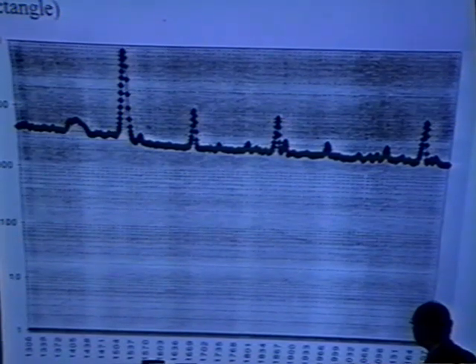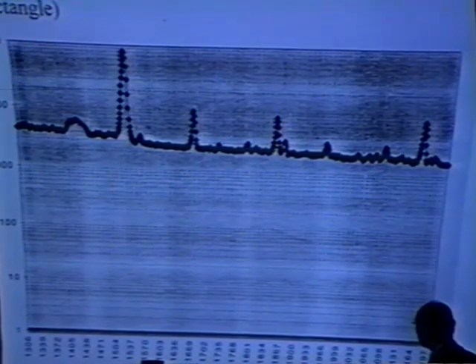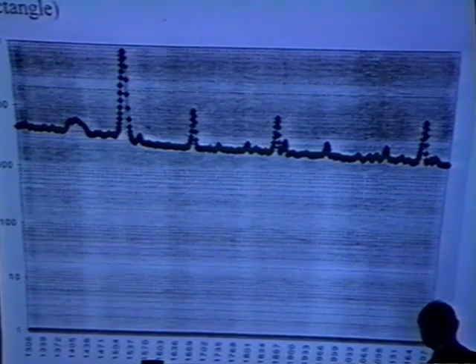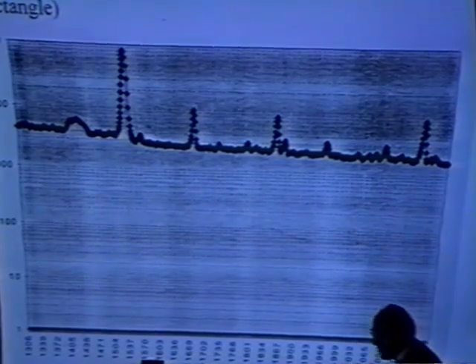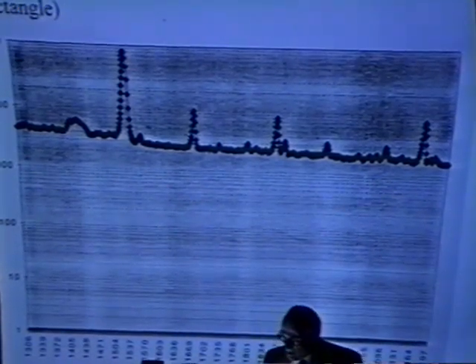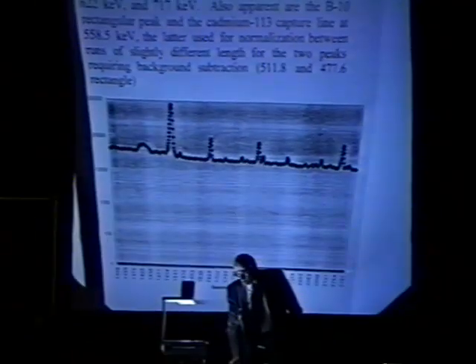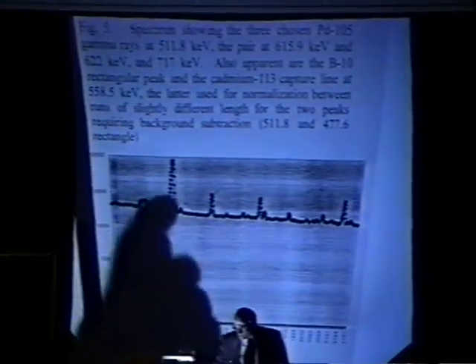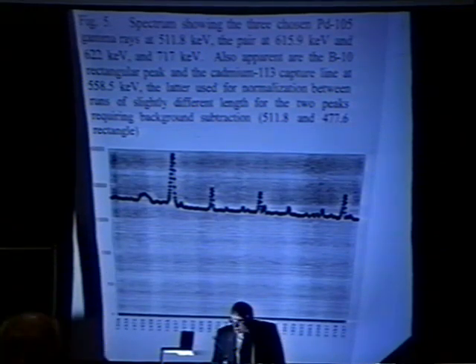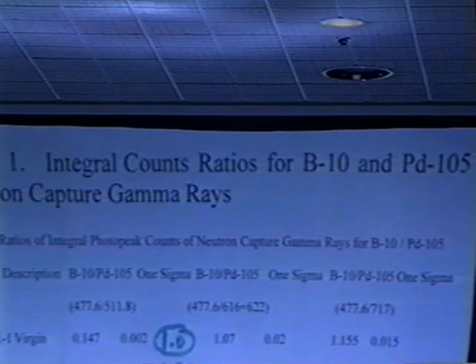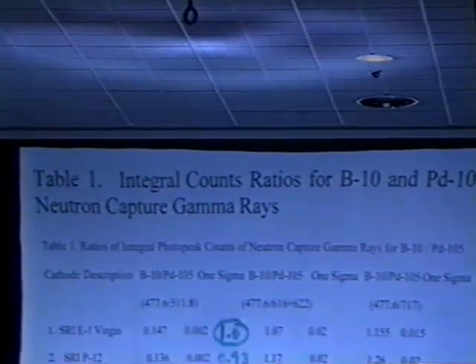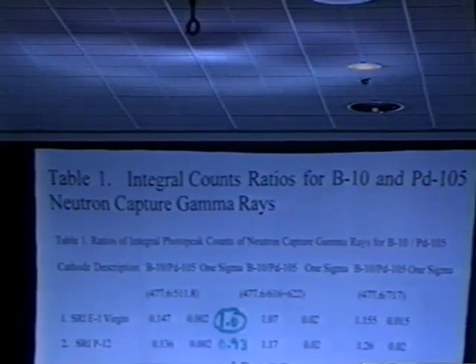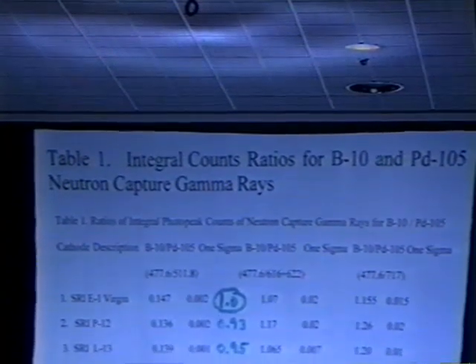And then here's the 616, 622 pair, also from palladium-105. Here's a 717 kilovolt gamma, also from palladium-105. So I have 3 or 4 ways, many others perhaps, to make this relative measurement of the area under these peaks relative to each other for the various cathodes. Now, here's some results, and I expect that you won't be able to do this here, but perhaps you can stop by my poster session and we can discuss to what extent these are logical reductions.